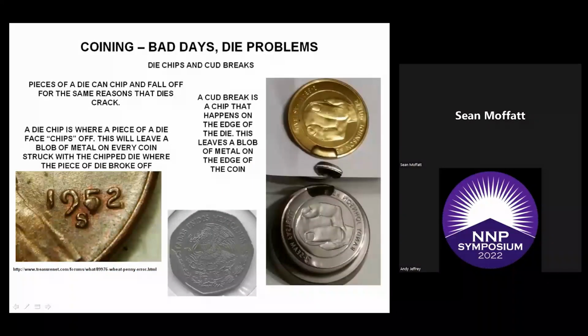And then we're going to have die chips and cud breaks. So pieces of a die can chip and fall off for the same reasons you get die cracks. And a die chip is where a piece of the die falls off, and this will leave a blob of metal on every coin struck with the chip die. So you can see a chunk in the back side of the 5 here broke off, and every coin made with that die that had that piece out is going to have this nice little blob in the middle of the 5.